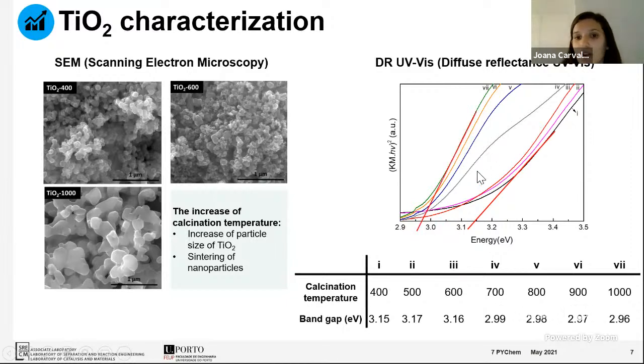When we change the calcination temperature, the material changes band gap. Looking, for example, at the material calcined at 1000 degrees, the green line, the band gap is 2.96. With this analysis, we can conclude that with an increase of calcination temperature, the band gap of the material decreases. This can be related to the increase of crystallinity and particle size with calcination temperature, and this way it can result in a lower rate of electron-hole recombination that will affect the photocatalytic activity of the material.